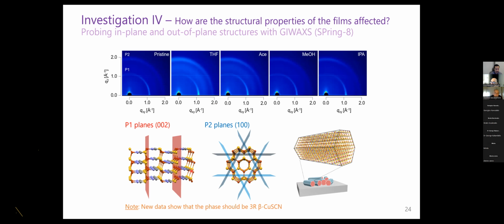This was the old analysis, when we still identified this as a hexagonal phase on the copper thiocyanate, but recently we actually found that it's a rhombohedral phase. But the directions of the planes are actually the same. It's just that the stacking layers from A B in the hexagonal would be A B C instead. But the overall directions of the planes are the same.